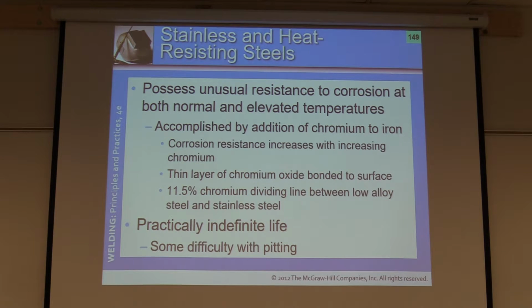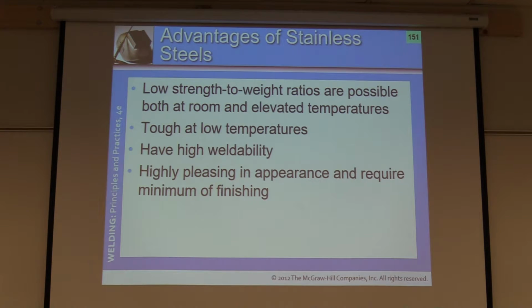Page 87, I want you to go to the right-hand column. Once you go to the very bottom, you see the two bolded items. Let's go up to the second paragraph before that, about a third of the way up from the bottom. The sentence starts out, pitting can be materially reduced. Okay, reading from the book. Pitting can be materially reduced by treating the area with strong oxidizing agents such as some chromates or phosphates. The addition of molybdenum to austenitic nickel chrome steels also helps control pitting.